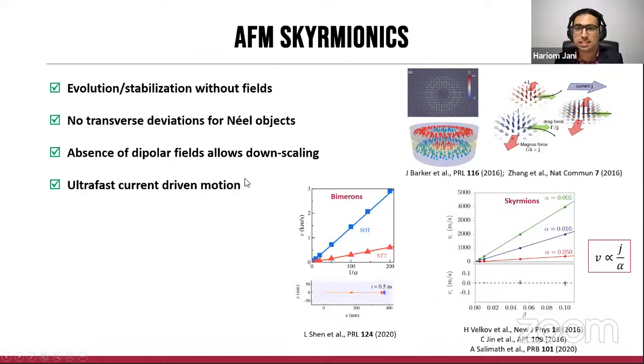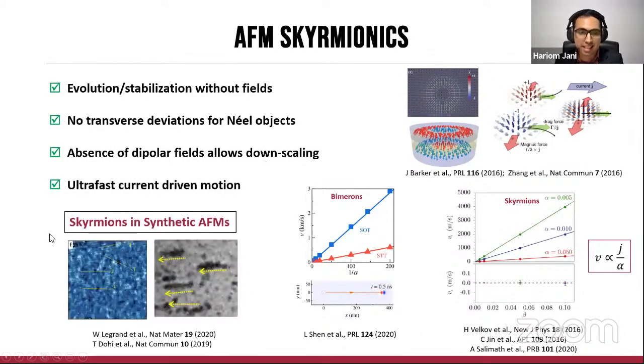To a certain extent, this investigation was realized, at least the stabilization part and the absence of skyrmion Hall effect, in synthetically coupled ferromagnetic layers. And these do seem to be promising. However, because synthetic AFM systems are coupled by the RKKY interaction, often the extreme limit to which they can operate is limited by the strength of the RKKY coupling, and beyond a certain limit, it would break down. So the interest is obviously always to go to natural antiferromagnetic systems and see if we can realize the body of skyrmionics in those materials.